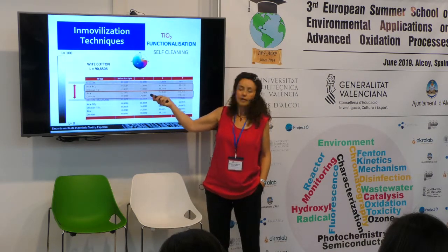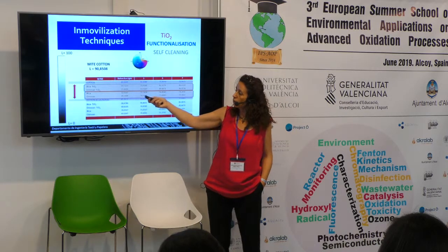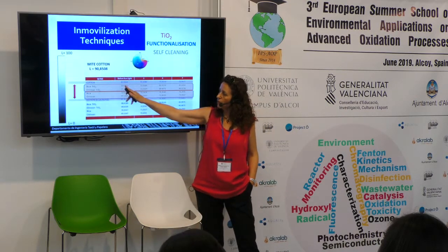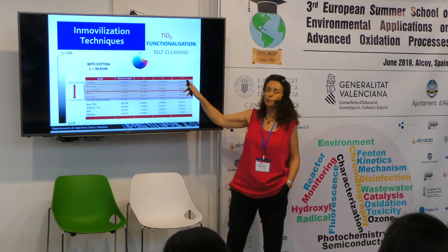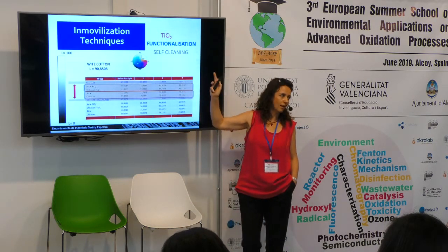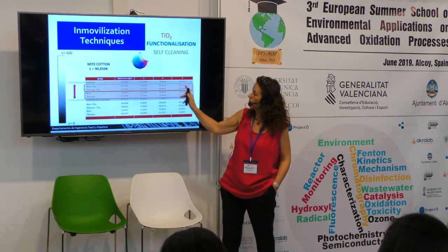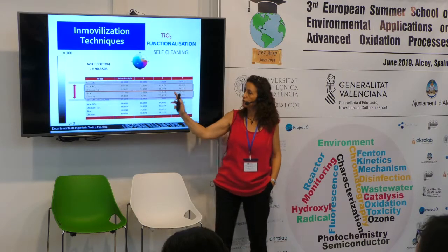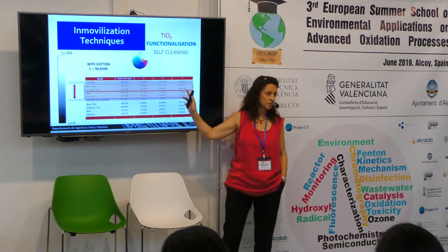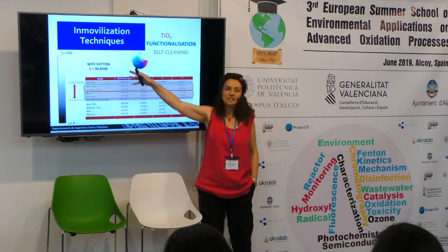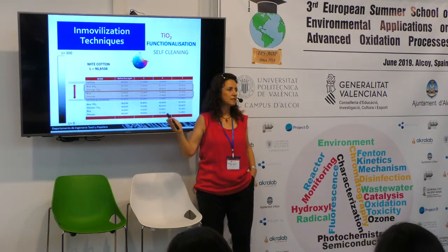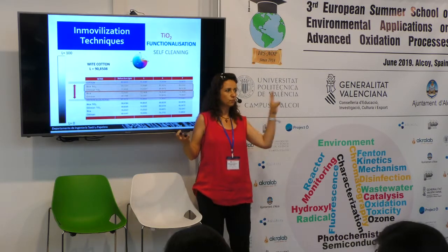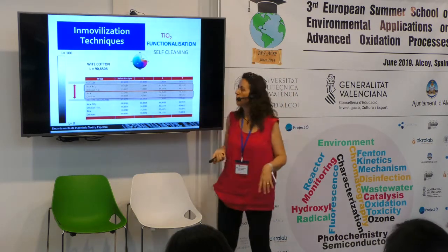We can observe that, for example, when we have the fabric exposed 7 days to sunlight, the value of the whiteness moves from 69 to 86, or from 71 to 86. So we do not reach 90, but it means that the titanium dioxide acted on the cotton, okay? And it moved towards whiteness.